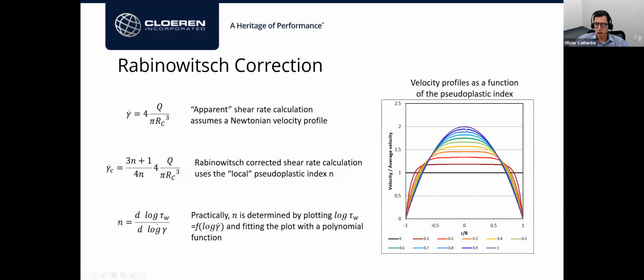A fully Newtonian material would be that dark purple color. As materials become more like shear thinning materials, more pseudoplastic or less Newtonian, the velocity profile tends to flatten, and eventually, even for a completely pseudoplastic index of 0, you have this black line here. Now, shear rate is the slope of this velocity profile at the wall. So as you can see, the shear rate is affected by how non-Newtonian the material is. The slope increases as the material becomes more pseudoplastic or less Newtonian. That's the correction proposed by Rabinowitsch, which uses the n value, a local pseudoplastic index.